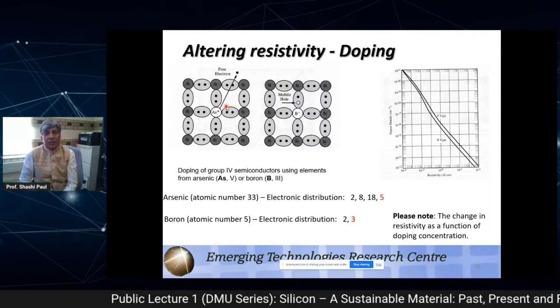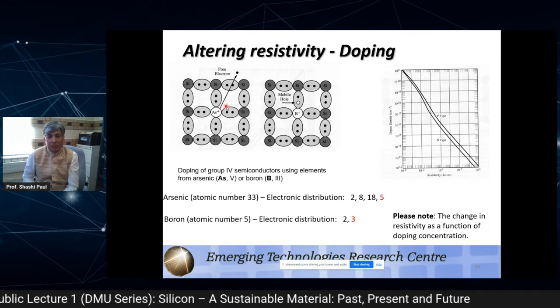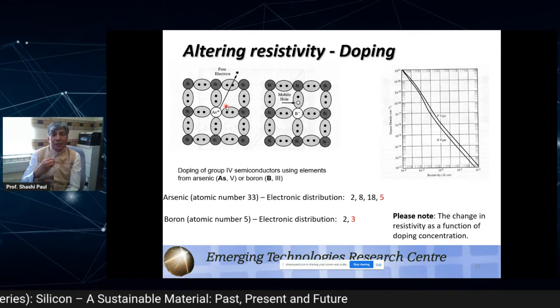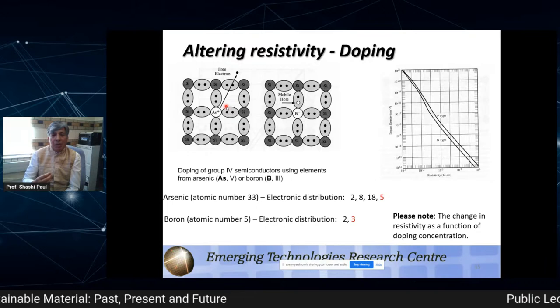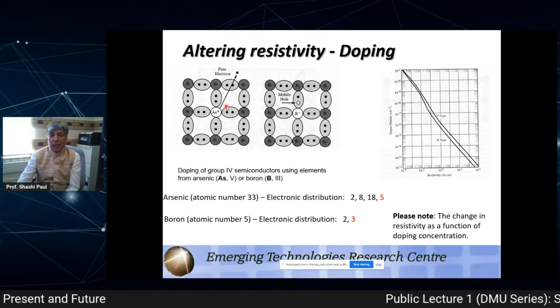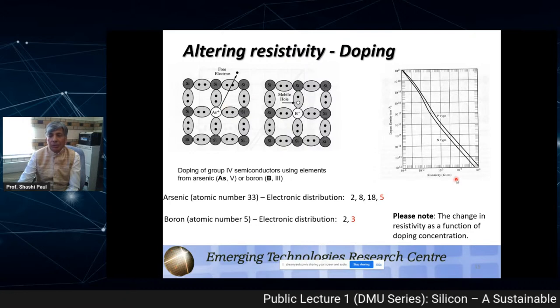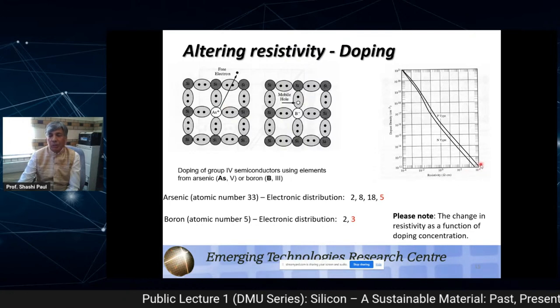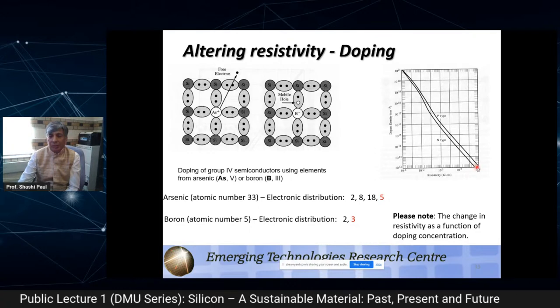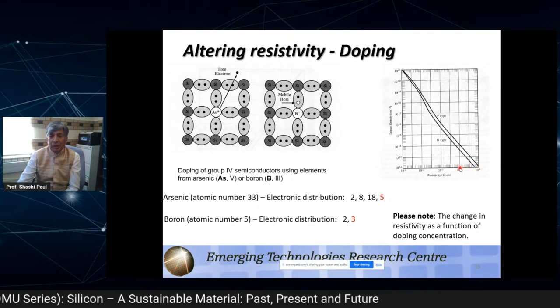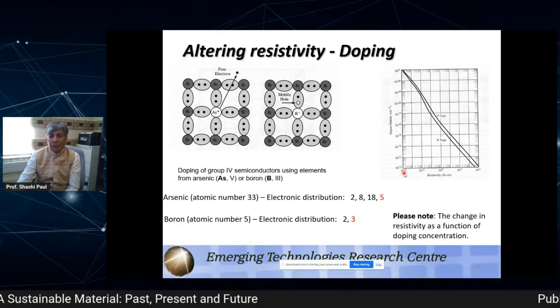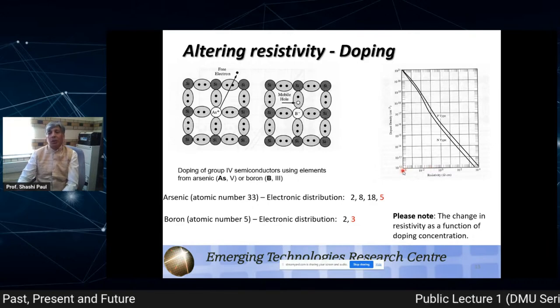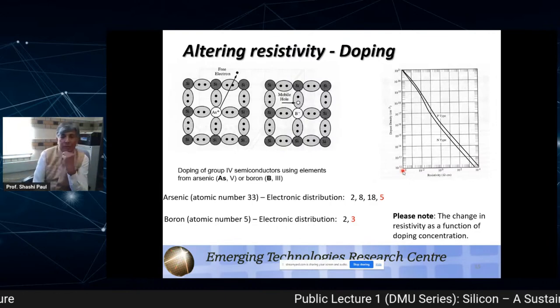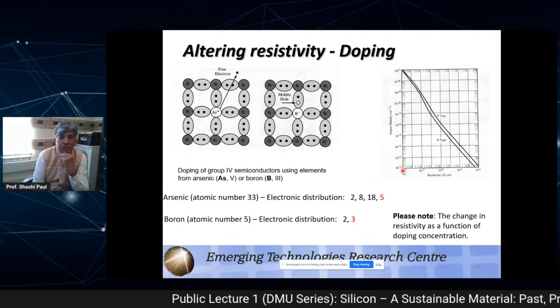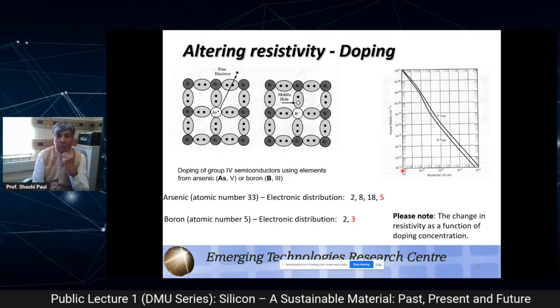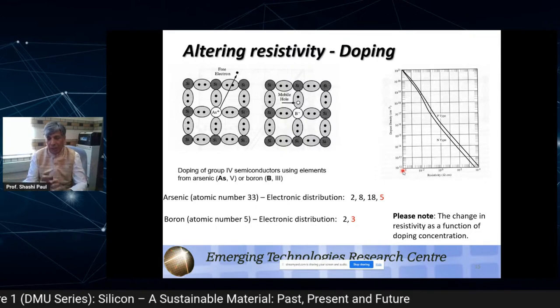an ordinary instrument can't detect whether you have put this arsenic or phosphorus in it. However, just by changing the concentration of these dopants, you can change the conductivity. For example, here is the resistivity. So this is 10 raised to the power 4. It means it's a very high resistance material. As soon as you start putting these things into it, you can have a resistivity very close to a metal. So this is the beauty of semiconductors. You can change their resistivity by many orders of magnitude by a process called doping. Okay, so that is important.